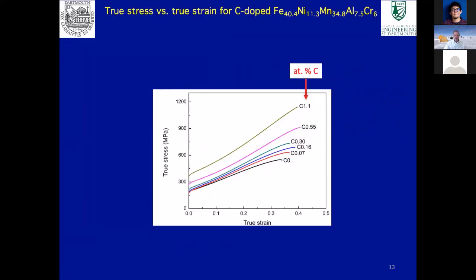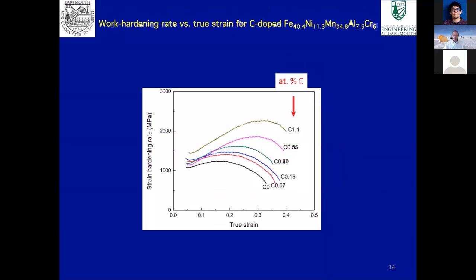So we looked at mechanical properties, and the really intriguing thing about these materials is, this is a material without carbon, and when we add carbon to the material, you can see 2 things happen. One is the yield strength goes up, the other is the ductility goes up, the elongation to failure goes up, which is an intriguing feature, to get both an increase in strength and ductility. The other interesting thing is what happens to work hardening rate. This is the material without carbon, and you can see the work hardening rate initially increases somewhat, and then it starts to decrease.